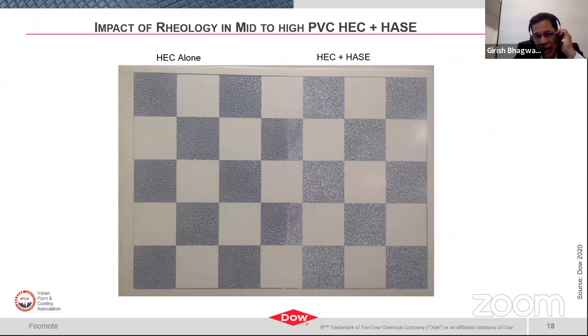So here I have tried to depict how the film buildup using a conventional thickener and a conventional plus HASE or associative thickener would deliver. If you see on the left hand side, the conventional thickener, here we use the example of an HEC. When you eventually apply with a roller, what happens is many times the paint has to deposit on the surface, but it actually flings off the surface because the roller tends to pull it back, and that's why the deposition is not there. Whereas with HEC plus HASE, now here also, not that it is great on flow and leveling, but there is a deposition which is ensured. That's why you see more opaque film and more deposition when you use an HEC plus HASE. So that's what is very important. Now this is just one coat. We could have applied 3 coats and it could have looked perfect.